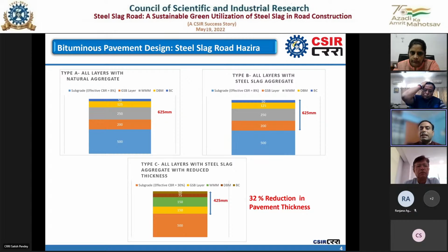First test section is a control section which has been built for the comparative study using conventional natural aggregate, and this section is designed for 100 million standard axle repetitions for 20-year design life. According to Indian Road Congress prevailing specification, the thickness of the section is worked out to be 625 mm for the road which is supposed to be built using conventional natural aggregate. So we kept the length of this control section around 200 to 250 meter, and another test section we built using 100% processed steel slag aggregate without reducing its thickness.